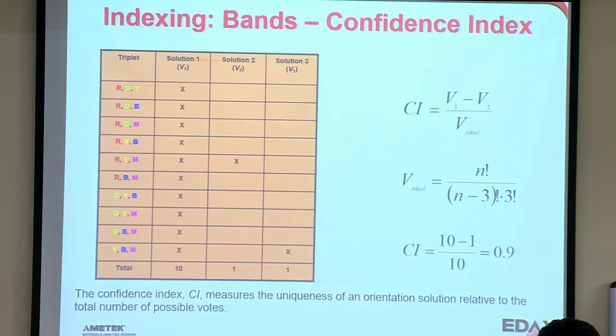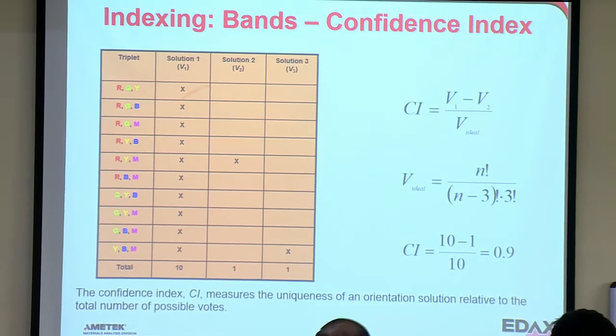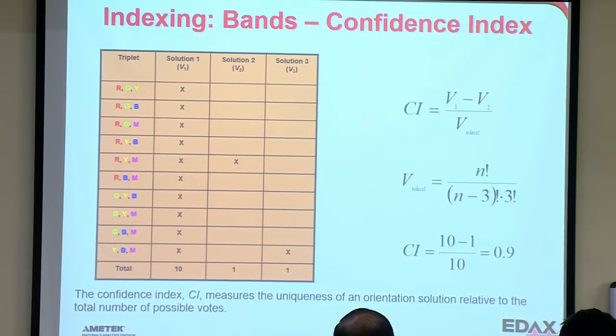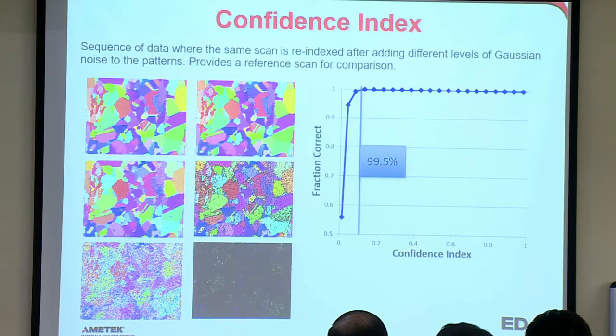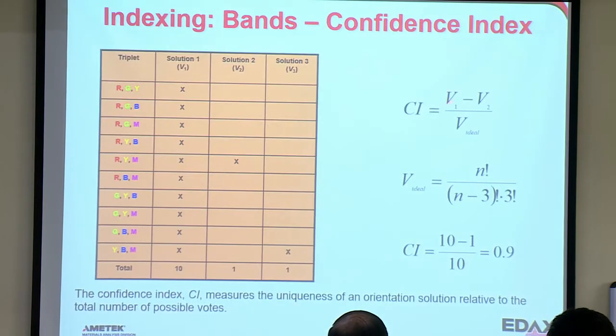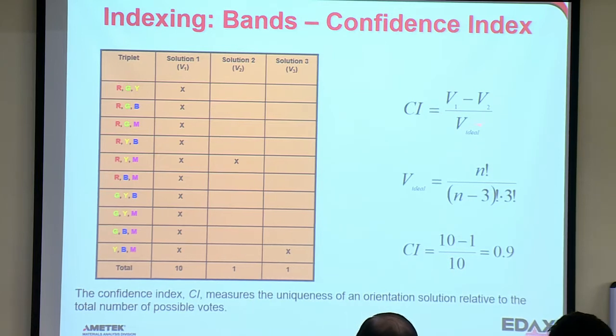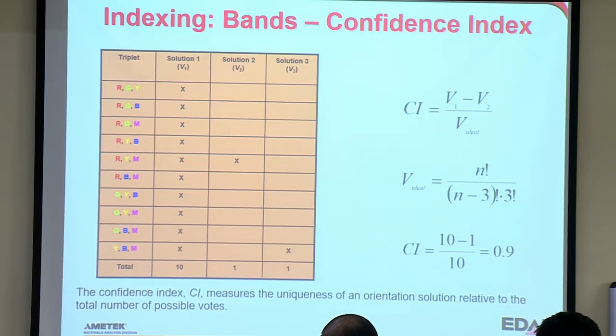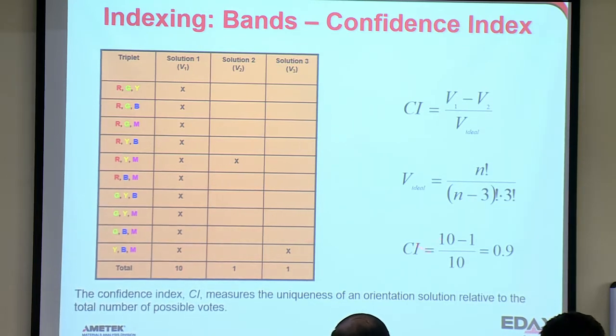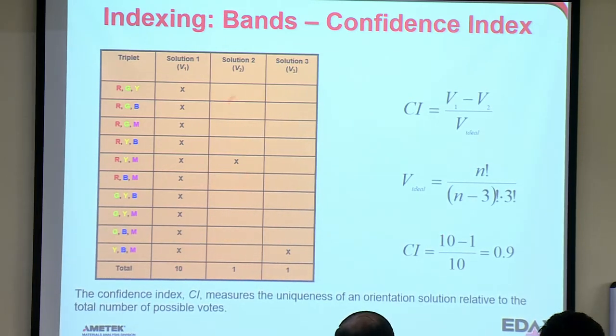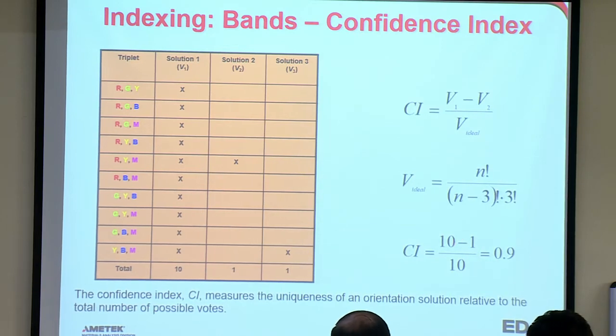And an important thing of this triplet indexing idea and this voting is we can calculate something we call the confidence index, or CI. The confidence index is equal to the top vote getter minus the second highest number of votes, divided by the ideal. So the ideal in this case is 10. The top vote getter is 10, and the second highest is 1. And so this would have a confidence index of 0.9.